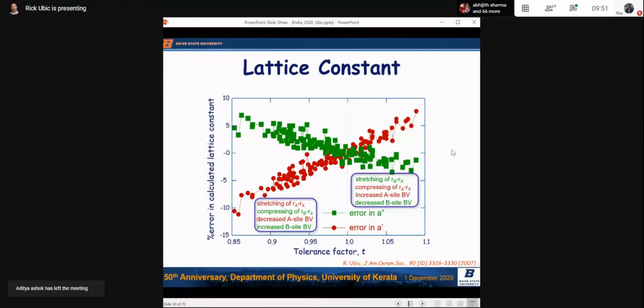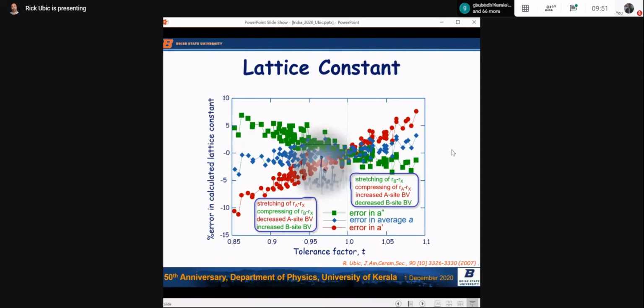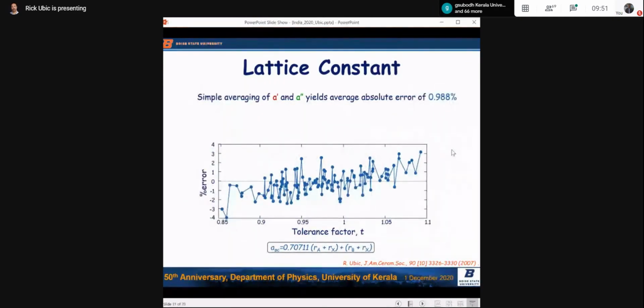So, we looked at this back in 2007 and said, what if we just averaged those? Wouldn't they average out pretty much to 0? Well, you can do that, and they average out close to 0. You get a better fit, but it turns out you can do even better than that. This is the average, right? If you use the simple average of A prime and A double prime, you get an average absolute error of about 1%, 0.988%. And there's the equation that would describe that situation. Less than 1% average error, that looks pretty good.